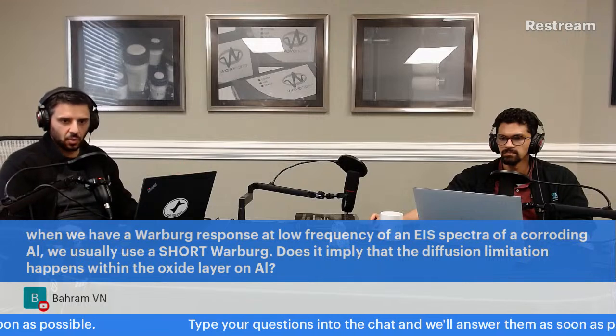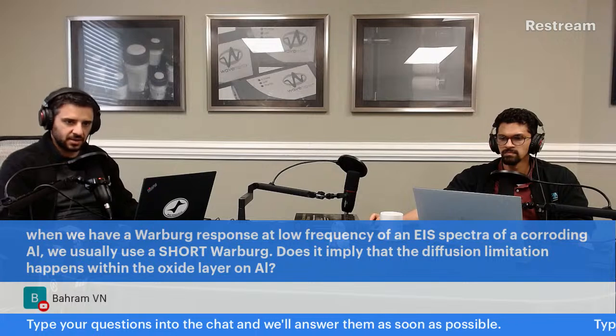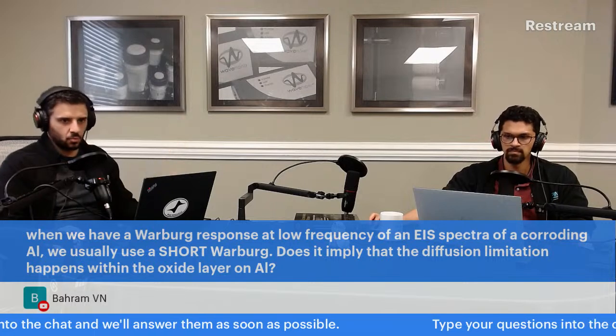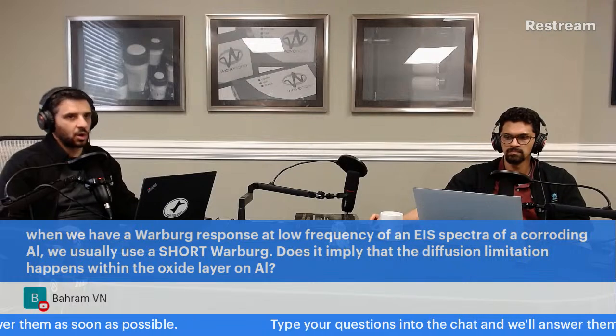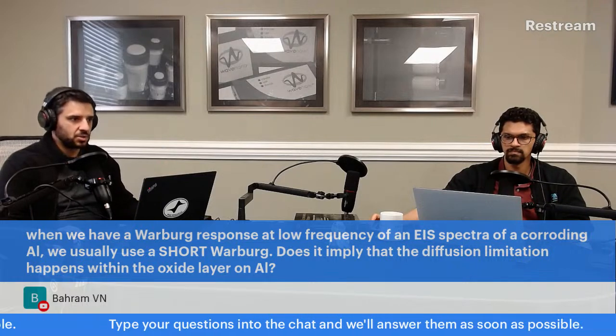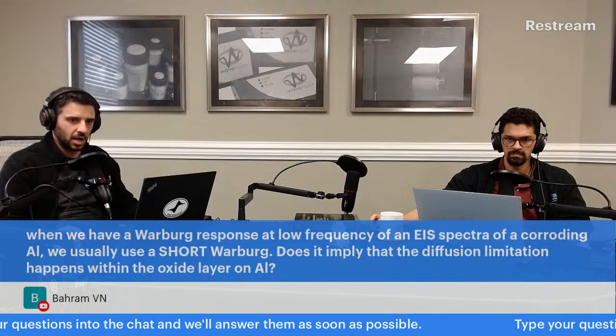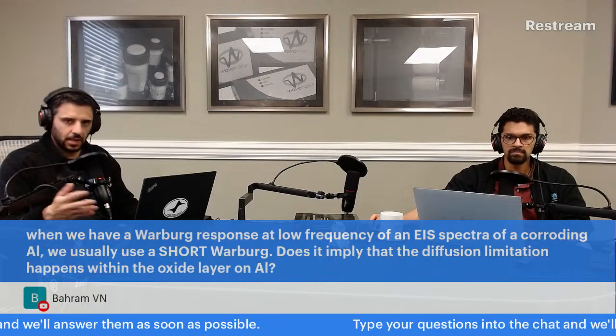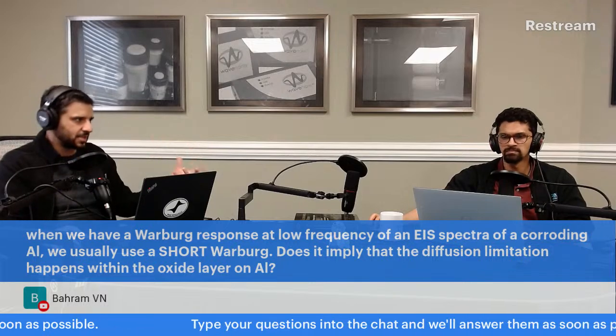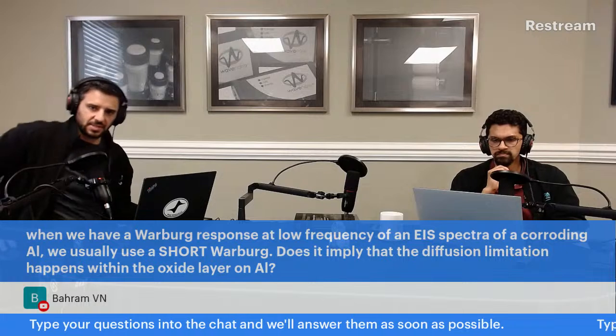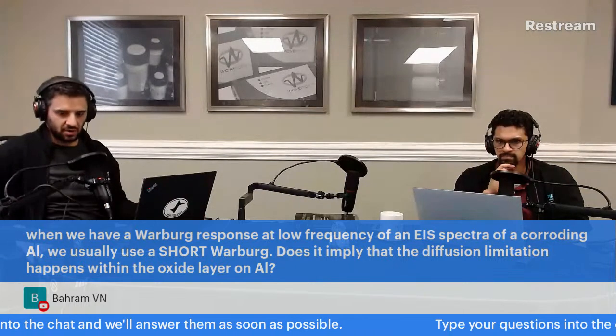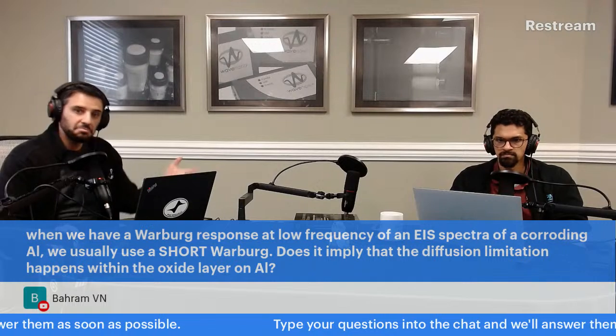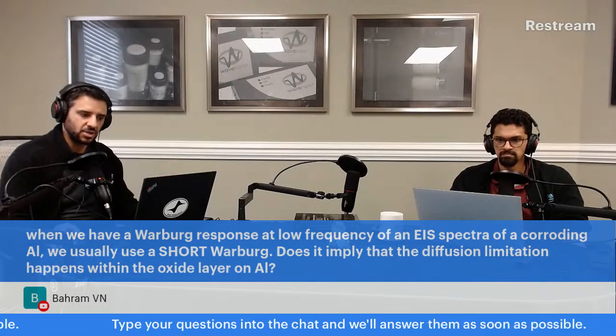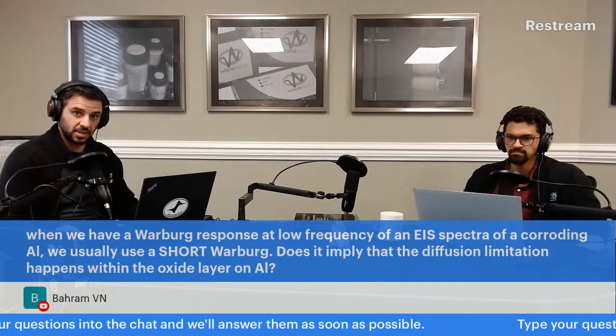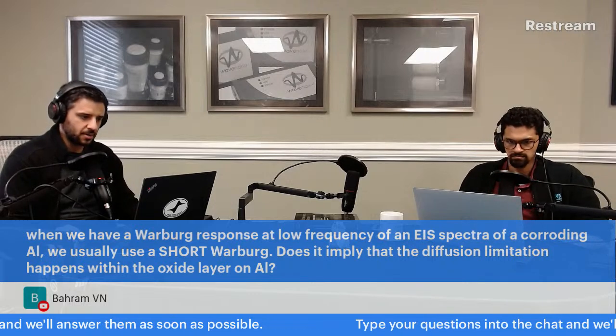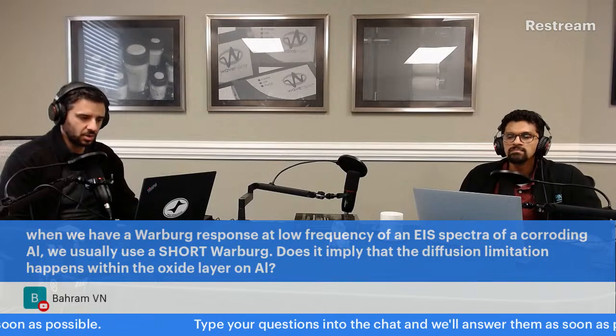Let's say you do the Warburg short and you determine that it is roughly 1 micron, or 100 microns, from the Warburg short, but you do a literature study and you find that the oxide layer is no thicker than a nanometer. I'm just making up numbers, right? Well, those are so far off, maybe that's not a proper explanation. Okay, so perhaps it's something else. But if you find that those are within an order of magnitude, let's just say, then that might be somewhat of a confirmation of your theory. But I do think that's a good theory. I think you're thinking the right way based on your interpretation of your Warburg short results.